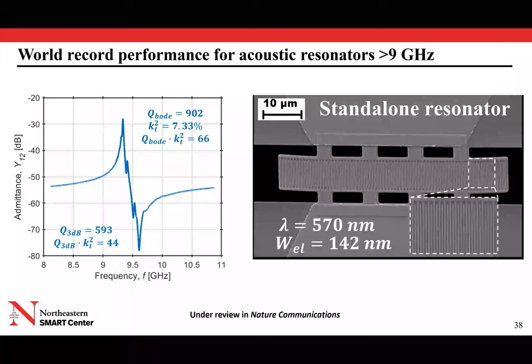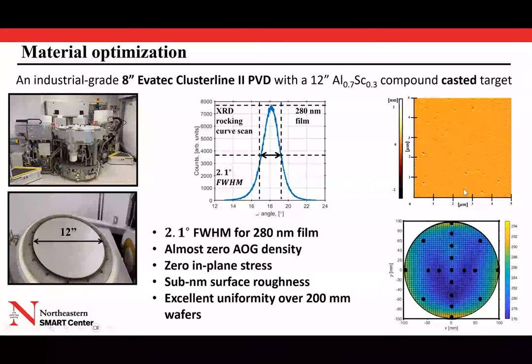Now, is this limited by material? I still think it is. I think the Q can be even higher than this. I went very fast here, but one big problem that we have with scandium-doped aluminum nitride is AOGs, or abnormally oriented grains, that form while we deposit the material. Some grains are not oriented in the right direction as we deposit the film. That has been a big problem with scandium doping of aluminum nitride. With time we were able to address some of these challenges. You see here these tiny dots in this AFM scan. The surface is very smooth, but there are still some of these AOGs.